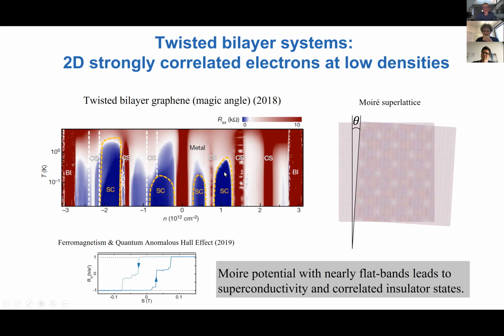But in between, you have regions where you see superconductivity, and these seem to be tied closely to regions where you see correlated insulator states, Mott-like states. Moreover, some of these actually exhibit ferromagnetism and the anomalous quantum Hall effect. So there's a long list of papers. This data is from Dmitri Efetov at ICFO, but the field was pioneered by Pablo Jarillo-Herrero. The idea here again is that as you introduce a twist angle, you change the alignment of the two layers in a way that a triangular lattice is obtained, and this is the superlattice potential that one gets.